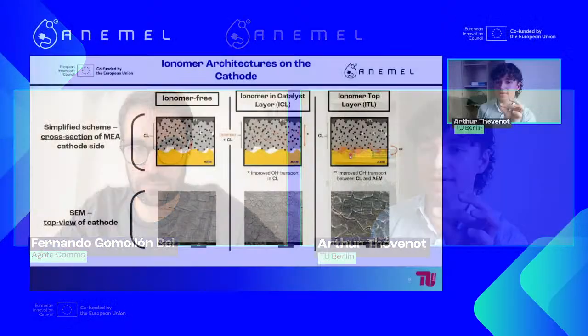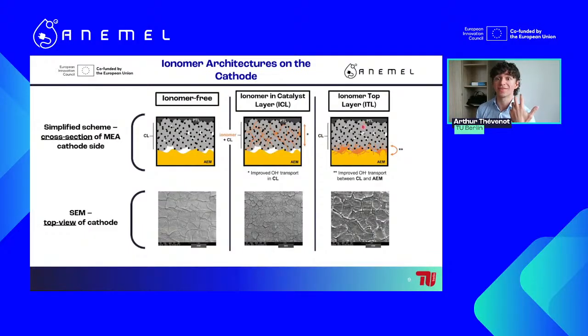So if I understand properly, the question was whether we observe some ionomer inside the catalyst layer despite having it spread over it. Is that so? Okay, I see. So for the ionomer top layer, we spread it on the surface, that is for sure. And originally there was no ionomer at all inside the catalyst layer. But it's indeed interesting because for our further studies to understand better the porosity and thickness of our system, it can be interesting to see whether while spraying, some of the ionomer penetrated a bit deeper, and therefore would not be pure surface, but also maybe a tiny bit more into the bulk. But hypothetically speaking, normally there should be no ionomer inside the catalyst layer. That would be interesting indeed to understand better the surface properties of the system.